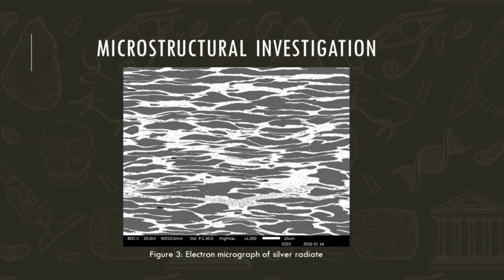metal. Following the visual inspection, I then completed the microstructural investigation, and the evidence from the Roman silver coinage also indicates that the coins were cast. This electron micrograph shown here is of the core metal of a Roman denarius minted under Septimius Severus. In the image, you can see copper-rich dendrites, which are dispersed amongst a silver-rich and eutectic matrix. The phases are elongated along the length of the coin, and this is indicative of striking.